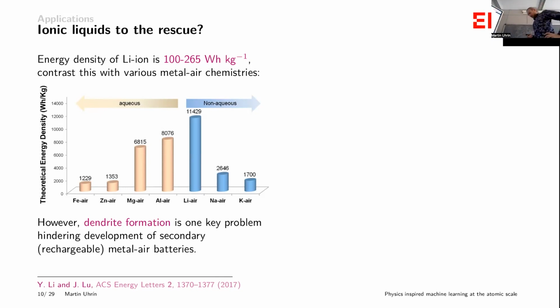ion that we have. But one of the big problems in these systems is, you can imagine, you've just got this pure metal sitting there. It's very, very reactive. It really doesn't want to be there. And as you cycle this thing, you actually start to form dendrites from the anode into your electrolyte. And then eventually that will just bridge the electrolyte and short circuit your battery, and then it's game over. So for that reason, you can already buy zinc air batteries that are non-rechargeable today, for example hearing aids, but there are no secondary batteries that are at least commercially viable. So tackling this dendrite formation for all of these systems is frankly probably the biggest challenge.